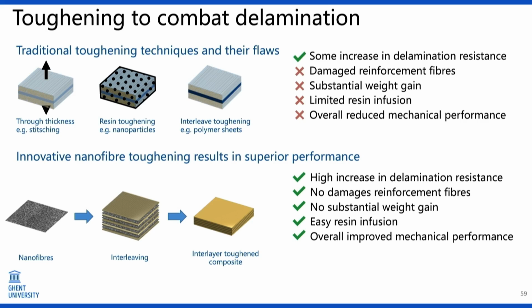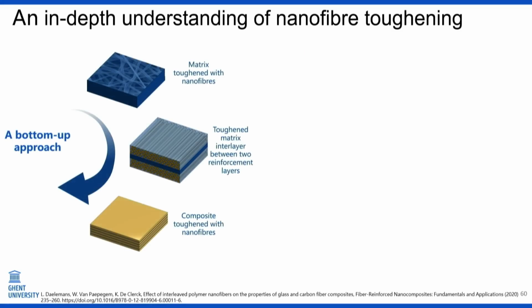So it can be introduced into the composite processing techniques which are used already today. And now I will show we indeed combine very high increases in delamination resistance, but with no damage of the reinforcement fibers, no substantial weight gain. We still have an easy resin infusion and thus an overall improved mechanical performance.